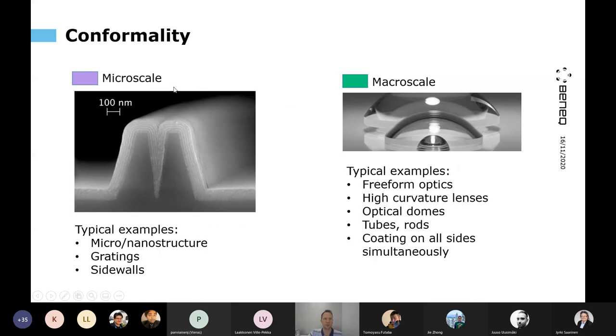Okay, so based on the way it grows, ALD can deposit very conformal films, and they can be conformal in the micro scale, so in the small scale, as shown here. Actually, in this image, there is a silicon substrate with a high aspect ratio structure etched into it, and then there is a multi-layer ALD stack that follows very nicely all those features. So there's 100 nanometers of alternating aluminum oxide and titanium oxide ALD layers.